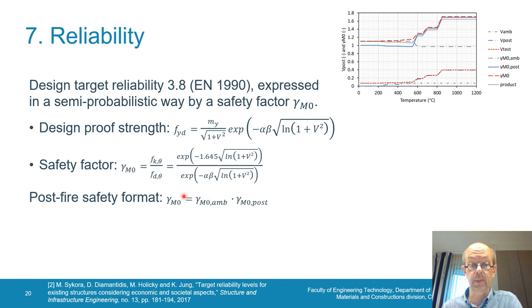The safety factor format means that the final safety factor is a product of the safety factor for ambient conditions, which is 1.1, and the one following the post-fire event. And it can be seen that till 550, the 1.1 is kept almost constant, and then we've got a second step, a third step, and a fourth step. But this is based with a reliability index of 3.8.